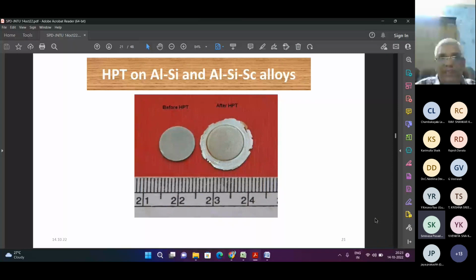like 1000 MPa. With aluminum alloys, if you are getting around 350, 400 MPa after heat treatment and after ECAP, that itself is great news. But getting 1000 MPa is really great news, and after we got these repetitive results, we thought we would present this to one of the sponsoring agencies like ARDB. Why? Because we belong to aeronautics structures, aeronautic boards.